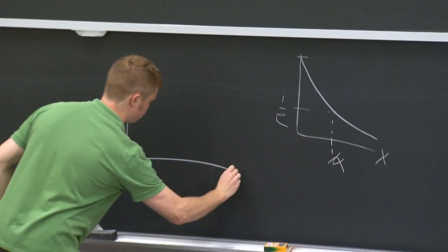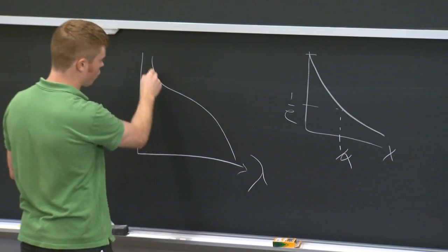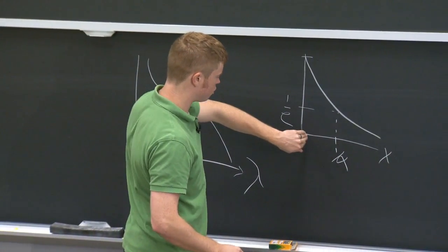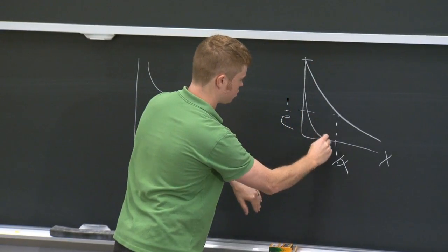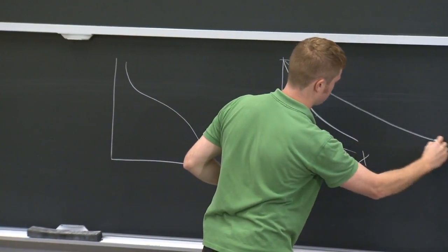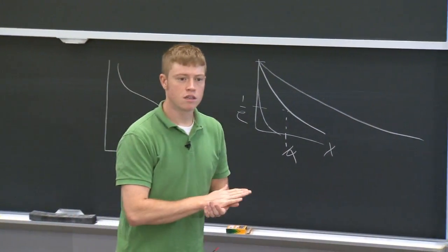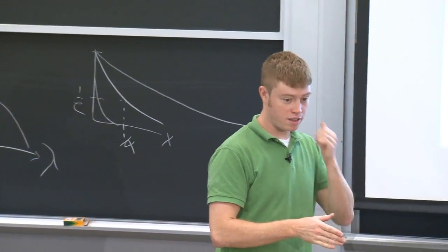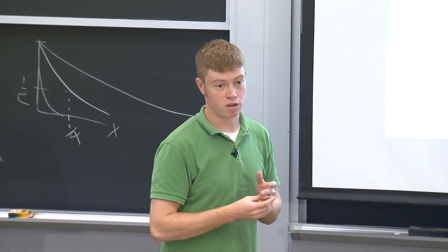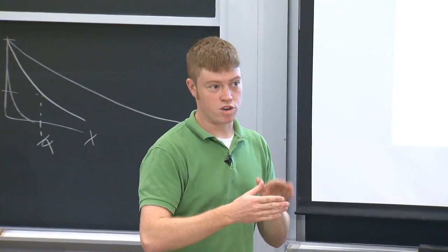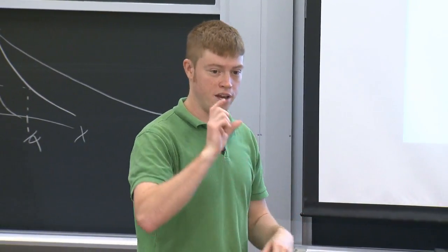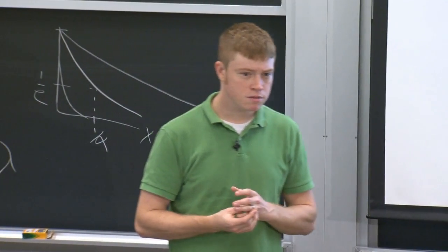If you recall, if you look at alpha as a function of wavelength for silicon, it continues to go down at longer wavelengths. So the short wavelengths are absorbed very strongly, and so most of the light is absorbed very, very close to the surface, whereas for the longer wavelengths, most of the light is actually absorbed very far from the surface. Does that make sense? And so there's a difference between your absorption length and your diffusion length. And that ratio is what's really important, right? If you're absorbing really far away from the junction, but you have a long diffusion length, there's a greater chance of it making it there. And it's that ratio that's really, really important. Does that answer your question?